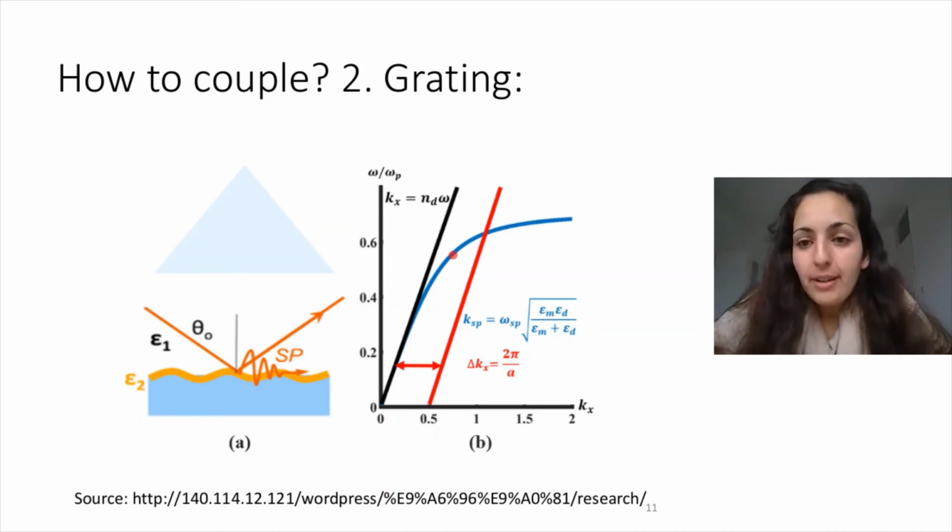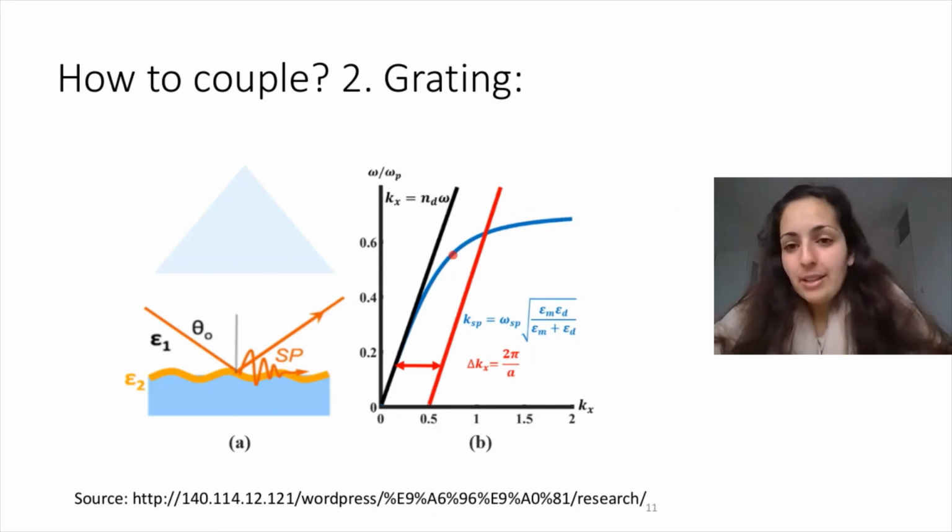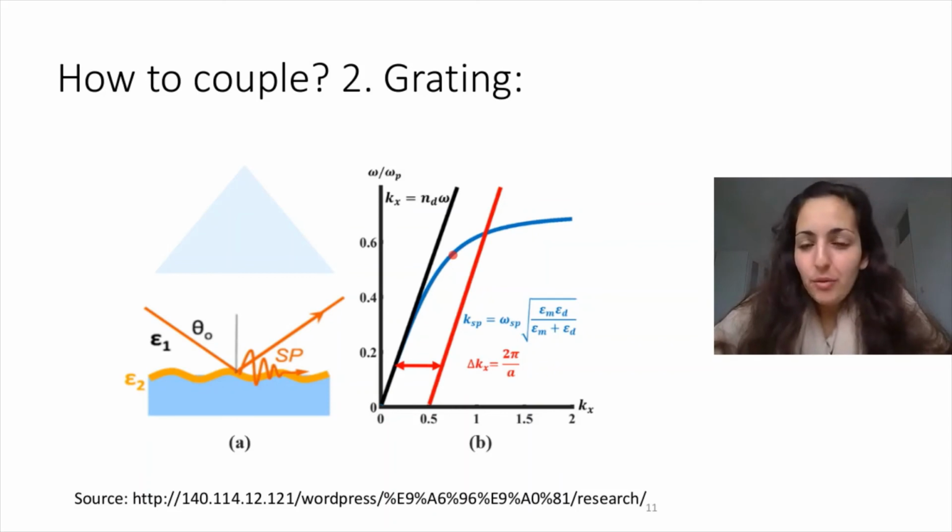And in fact, there you can often observe plasmon absorption or unwanted excitation of plasmons, and thereby unwanted absorption, due to the fact that the surfaces are not perfectly smooth, but you always have a little bit of roughness, and that then gives you surface plasmon excitation, although you didn't even design it for it. So it can even be an unwanted effect.